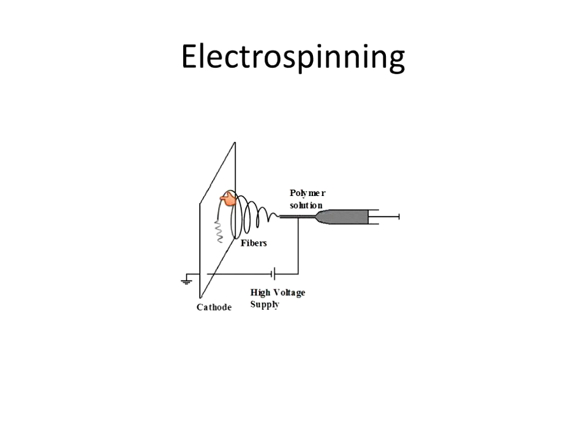So there are many uses in biology for this technique. In my experiments, we need just one fiber. As you can see over here, from the tip of the needle to the cathode, a distance of about 15 to 20 centimeters, you get several fibers. And how does one get a single fiber? To get a single fiber, what I do is I take a substrate, and in the space between the tip of the needle and the aluminum foil, I quickly go down in a very fast downward sweeping action. That gives me a few fibers on the substrate.